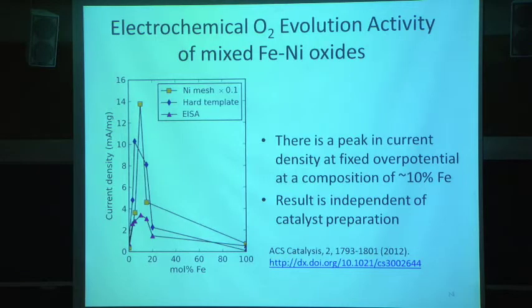Right, and this is what the results look like. So you start over here at pure nickel oxide. You get pretty reasonable milliamp per milligram loading of catalyst. As you go through about 10%, you see a huge increase in activity, and then as you add more iron, it comes back down. Now, interestingly, this nickel mesh, if you notice over here, is times 0.1. So that nickel mesh was 10 times more active than all of these high surface area materials.